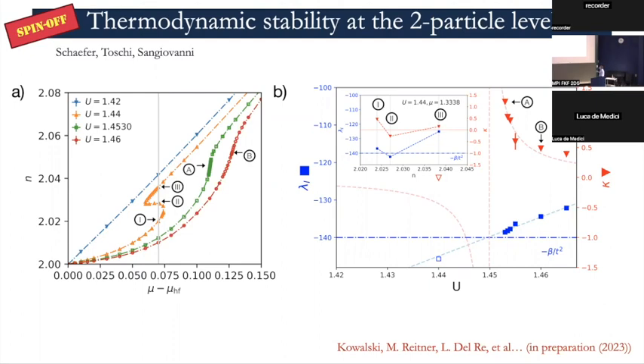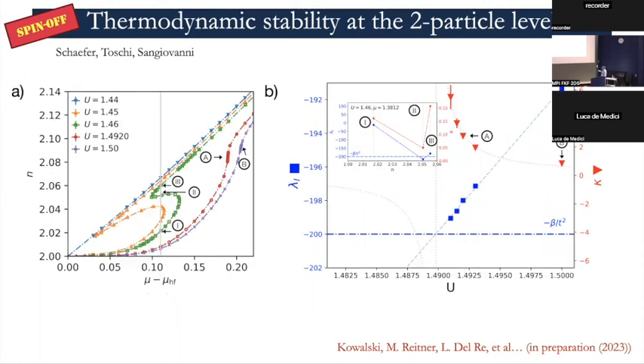So now if you analyze these curves in this sense, going through the positive compressibility, negative compressibility, positive compressibility again, which is this path over here, red is the compressibility, you see that the eigenvalue goes from above to below the threshold. So it's really a local calculation that tells you if the system is stable or unstable. And this is just some lower temperature in which indeed you have this weird positive compressibility branch, but which is still unstable. The compressibility will remain positive, but the eigenvalue will still tell you, going below the threshold, that the system here is unstable. So it's really a calculation where you can do one shot on your solution, and it will tell you if the system is stable or unstable there without having to resort to thermodynamic derivatives.